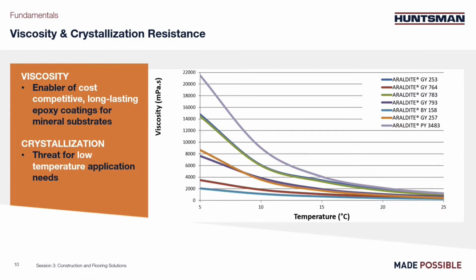Another important parameter is the crystallization resistance. It is very difficult to reverse crystallization of chemicals. Actually, it's kind of impossible if you are on site, because if you want to melt a crystal, you generally need to reach 70 degrees C while you are mixing the resin. So we have designed specific resins like Araldite GY 783 and GY 793 in a way to avoid this crystallization. Those two resins generally fit the self-leveling and top coat applications.